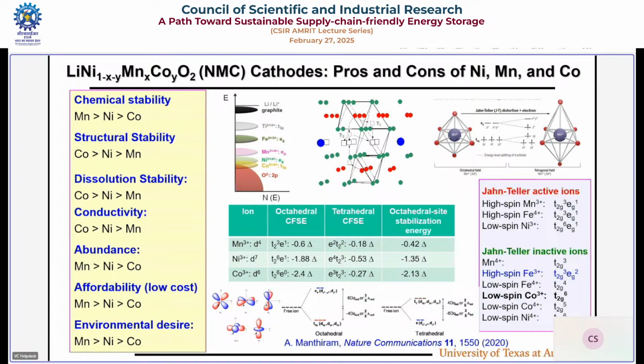2 factors are important. Physics people here, you will appreciate. Chemistry people here, you will appreciate. Inorganic chemistry people are here. Crystal field splitting and all those. First, the cobalt 3+, 4+ band overlaps with the top of the oxygen 2p band. So if I charge that material more than 50%, if I remove more than 50% lithium, I will be removing electrons from the oxygen 2p band, the oxide 2p band. If I do that, I am introducing holes into the oxygen 2p band. That means I am oxidizing oxide ion to peroxide, superoxide, and oxygen. So it will evolve gas, a safety problem.